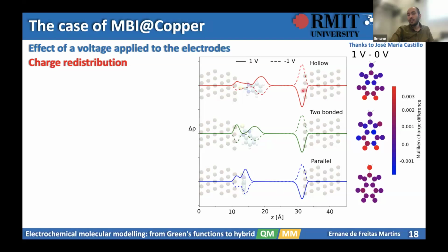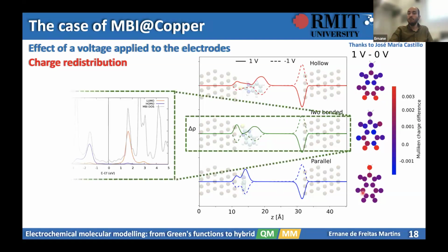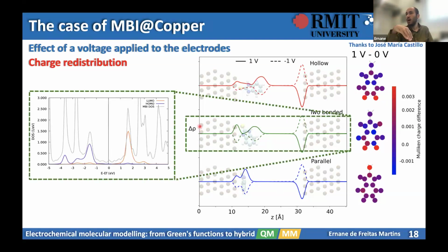And on the other side, everything behaves as expected because we don't have a molecule there. So the application of the voltage leads to an accumulation of charge at this adsorption site in the tail of the molecule. And here, since it is parallel, it is distributed in the molecule. If we take one example and look at the density of states, so how the electrons are distributed for each energy, we see that the lowest unoccupied and the highest occupied are close to the Fermi level. That's why the molecule can get charged and discharged because of the voltage.